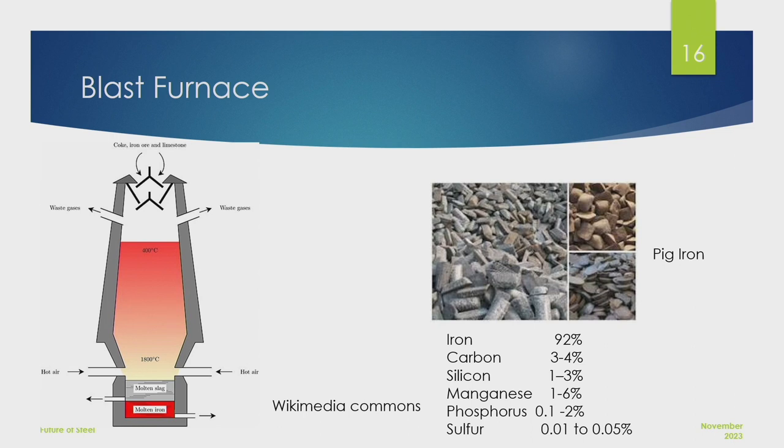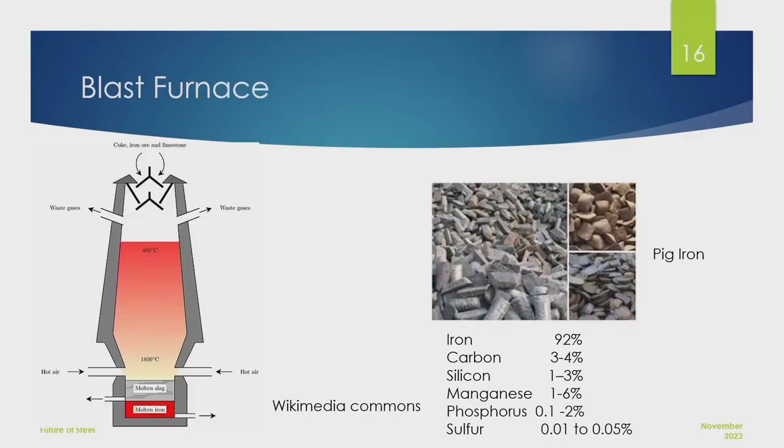When they started doing shaft furnaces, feeding material in at the top, you put the iron ore in, you'd put the coal in, you'd put some calcium-bearing materials in, and then do it in levels, and you'd blow the gas through it. You would burn the gas at the bottom, get it hot, you'd have a tall enough material so that as it went down, it got hotter and hotter. And then you had a liquid at the bottom, you get two liquids. You get the liquid iron, carbon alloy, and then you get the gangue material, which is now reacted with carbon, with calcium, to form a calcium silicate, a liquid slag, and you could pour the liquid slag off one side, you could pour the liquid metal off the other, and now you had a continuous process.